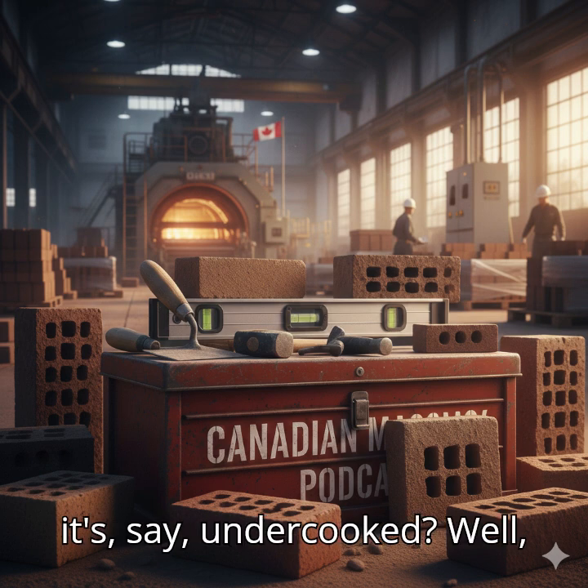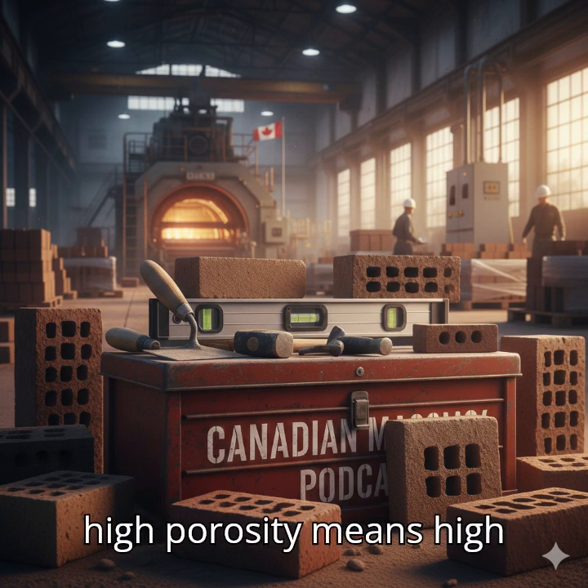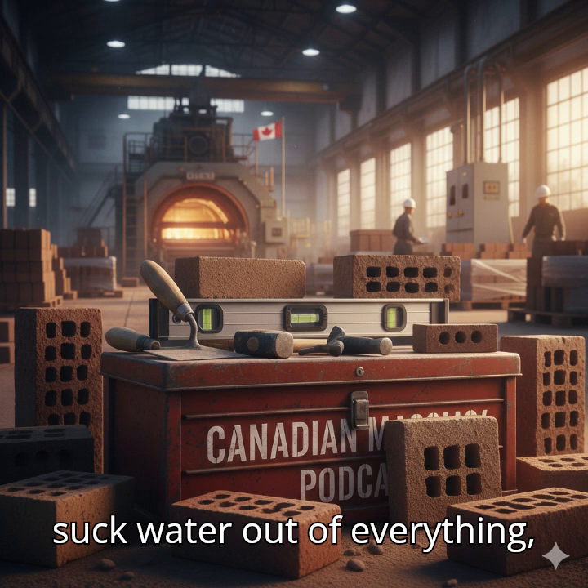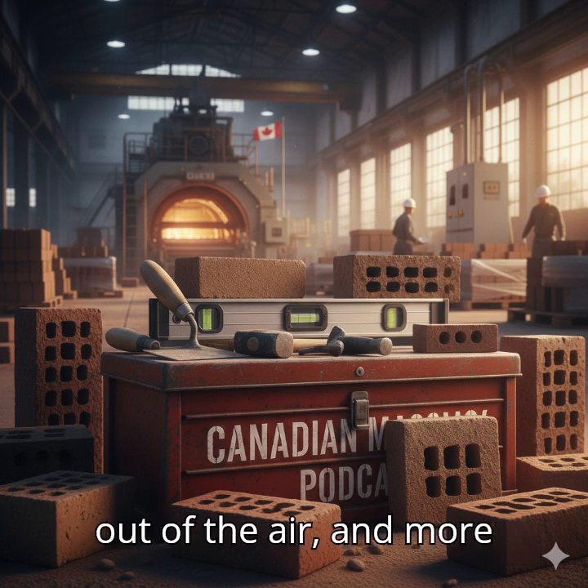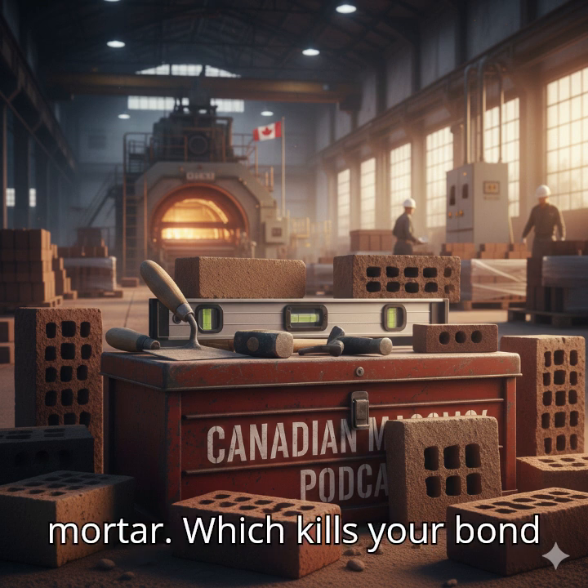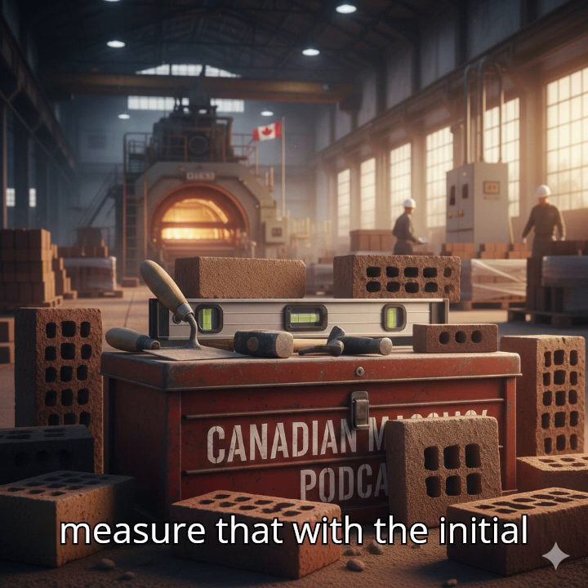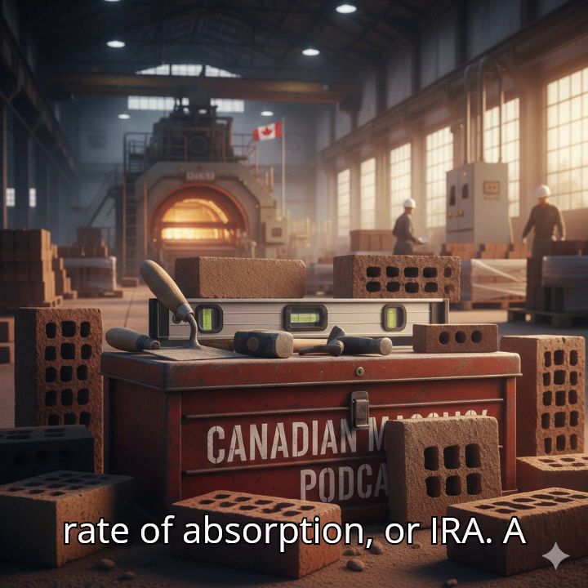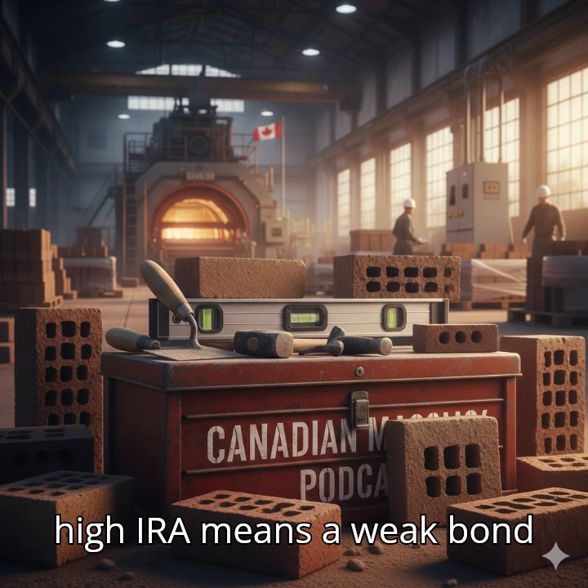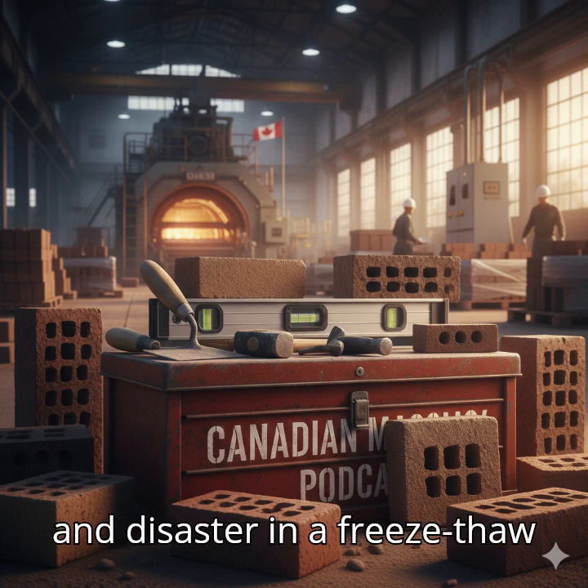What happens if it's, say, undercooked? Well, high porosity means high absorption. That brick will suck water out of everything, out of the air, and more importantly, out of your mortar. Which kills your bond strength. Kills it. We measure that with the initial rate of absorption, or IRA. A high IRA means a weak bond and disaster in a freeze-thaw cycle.